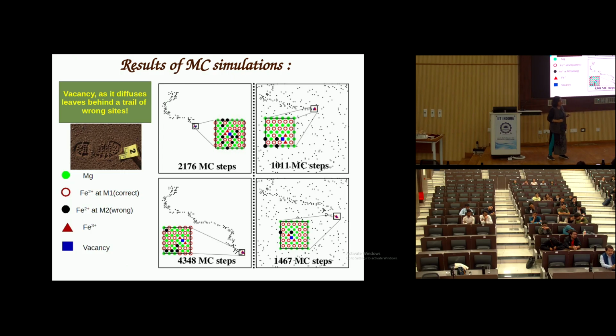It's exactly that. So this is for some small time scale Monte Carlo, for longer time scale, and you see this trail of wrong sites it creates. And we said that your crystal is not perfect. Maybe to start with, there was some randomization between M1 and M2. That is the situation. But even then, you can identify this trail, because this trail is very, very directed, extremely directed, because the vacancy always prefers this M1 site. And there is a certain trail of this M1 site. And since the wrong site follows where the vacancy has moved, it follows exactly that trail.